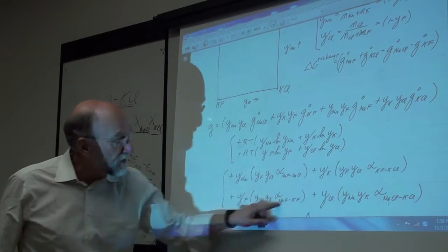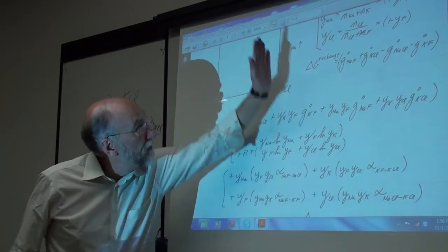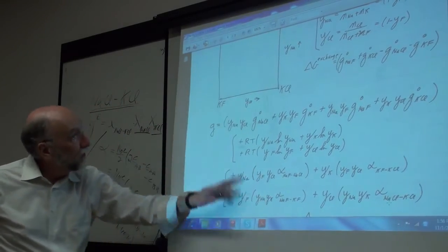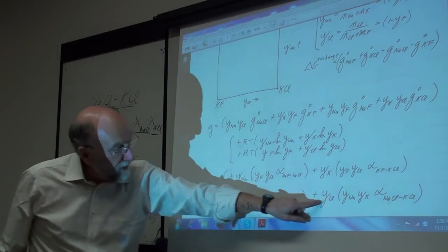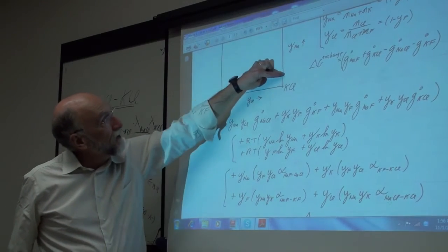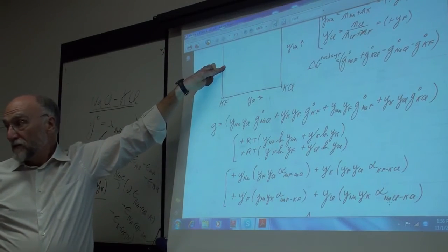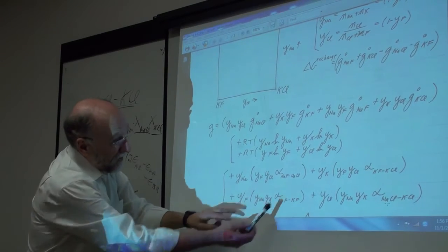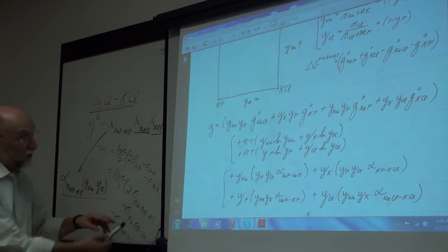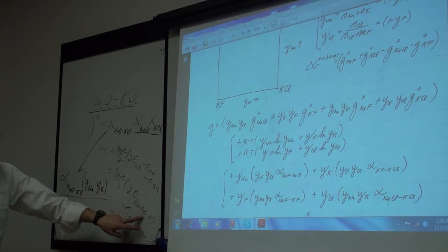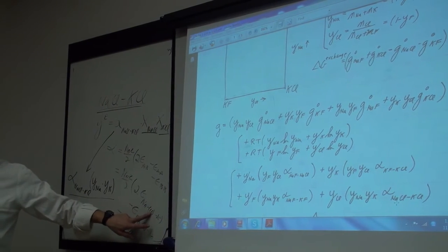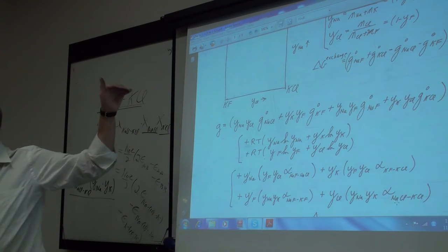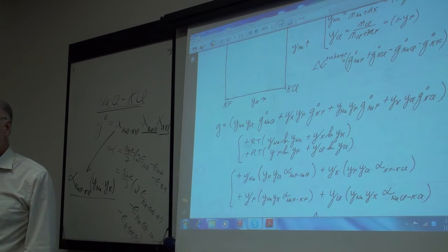These last two terms here, this is the binary term on this side, this is the binary term on this side, second nearest neighbor binary terms, and the binary terms in the ternary just vary linearly between the two sides. These are second nearest neighbor sodium-potassium bonds, but on one side they're sodium-potassium separated by fluorine, which will have a different energy than sodium-potassium separated by chlorine, so we just vary them linearly from one side to the other.